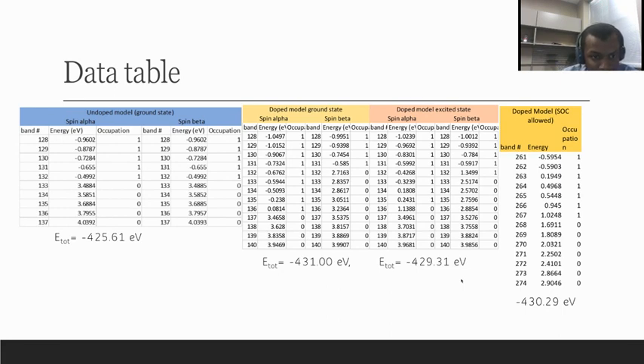And also from the first data table, we can predict what the PL would be after excitation. That would just be the band gap, or the energy difference between the HOMO and LUMO orbitals, right? Yes. For example, for alpha, the difference between HOMO alpha and LUMO alpha is about 3.5 electron volts, which corresponds to a photoluminescence of around 350 to 400 nanometers, which was experimentally proven to be true, and was seen during experiments with Aaron.